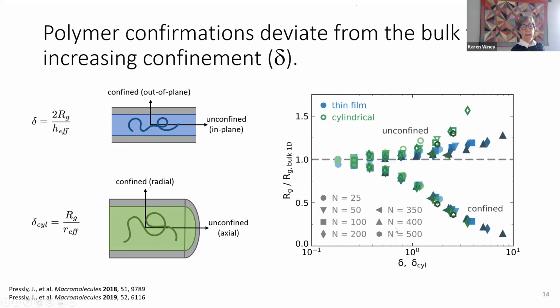And what's interesting is if we plot the radius of gyration relative to the bulk as a function of this confinement parameter, the cylinders and the thin films have the same level of deviation from the bulk in the confined direction. And then in the unconfined direction, the thin films are a little less deviated than the cylinders, because the cylinders are curving around and further distorting the chain conformation from the bulk.